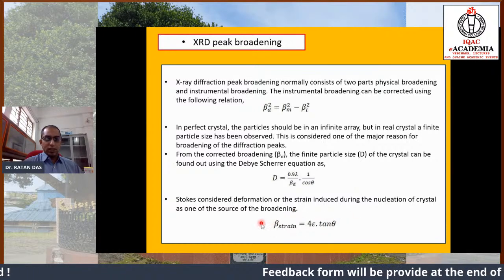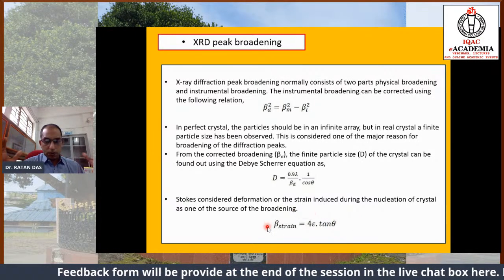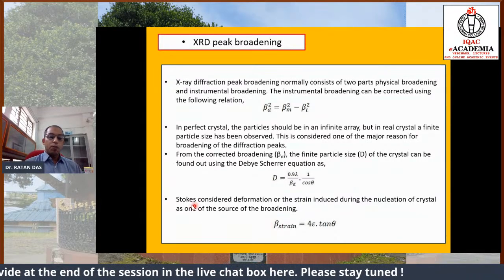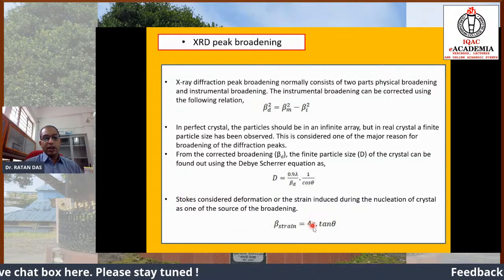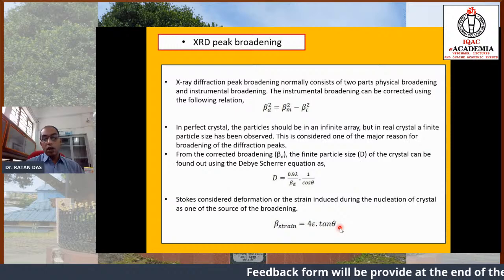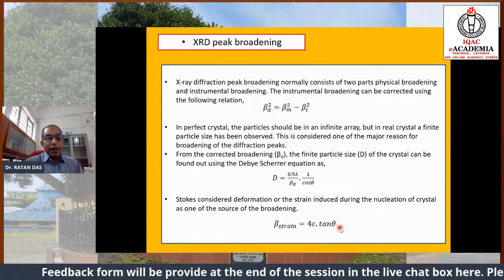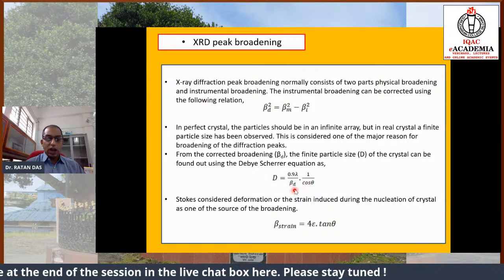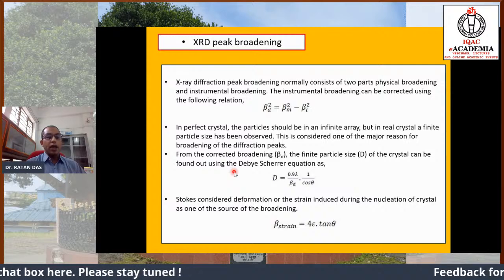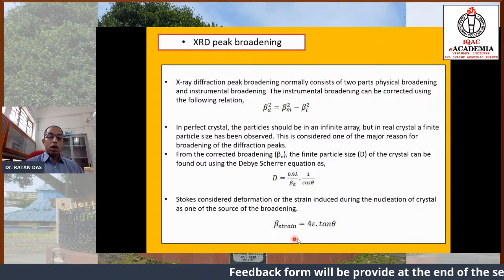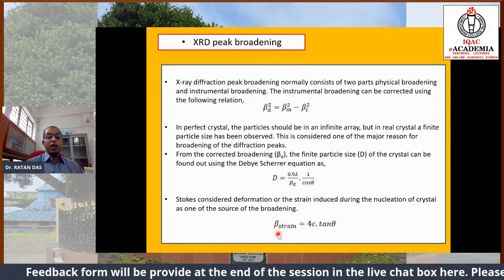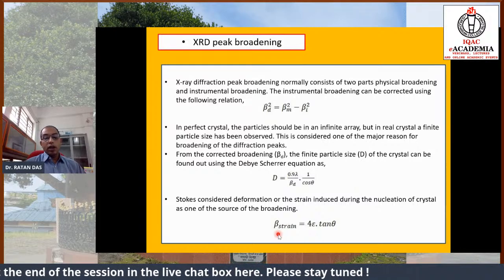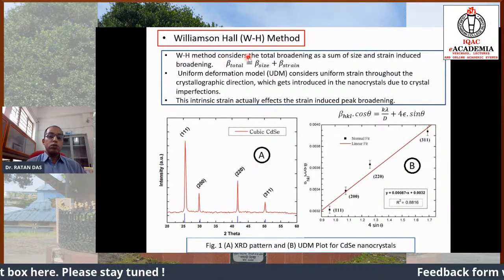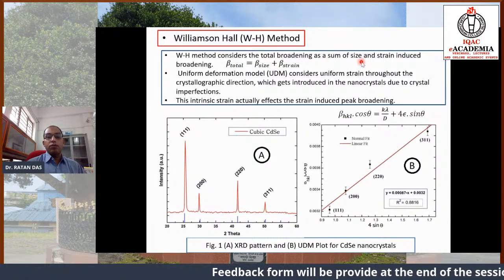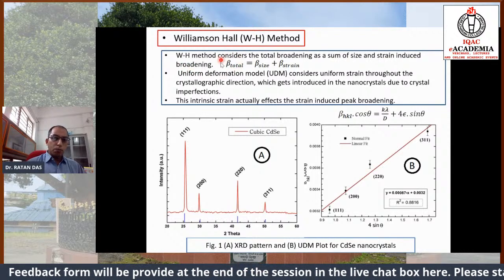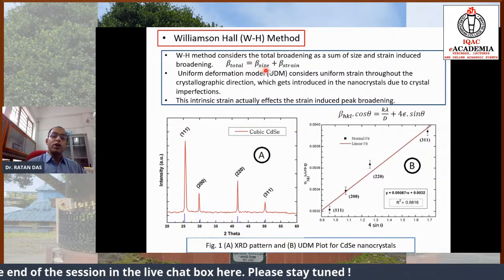Don't ask me how you can obtain these things. It is not the time to discuss obtaining this particular 4 epsilon tan theta. But take it for granted that Stokes through various methods gave the idea that the strain term is 4 epsilon tan theta, and he actually made those beta strain and beta size in the full width at half maxima. He told that the full width at half maxima is a combination of the effect of size as well as strain, and this combination actually gets reflected in the Williamson-Hall method. Williamson-Hall method considered the total broadening as a sum of size and strain induced broadening. So total broadening of the X-ray diffraction pattern is nothing but the convolution of size and the strain effect.